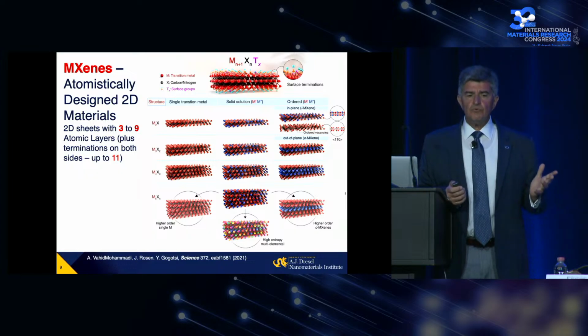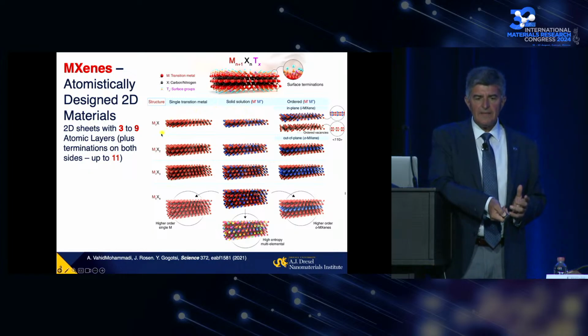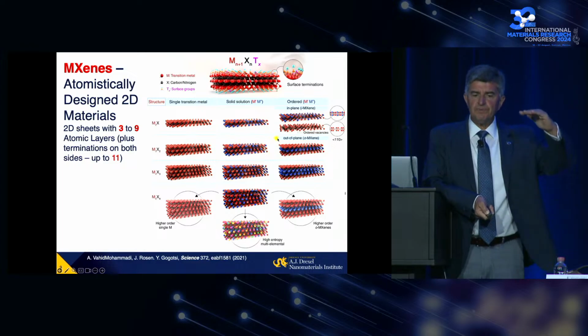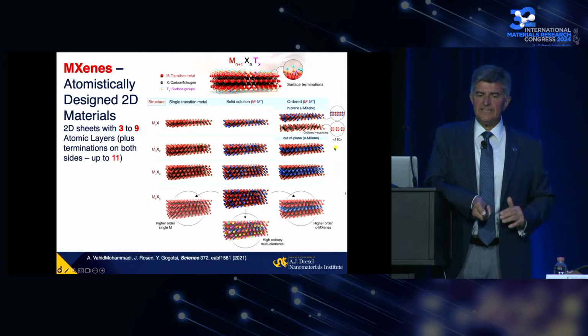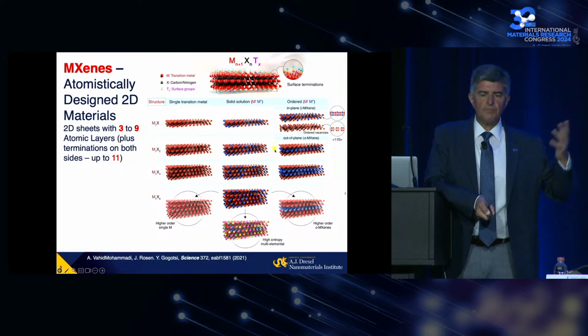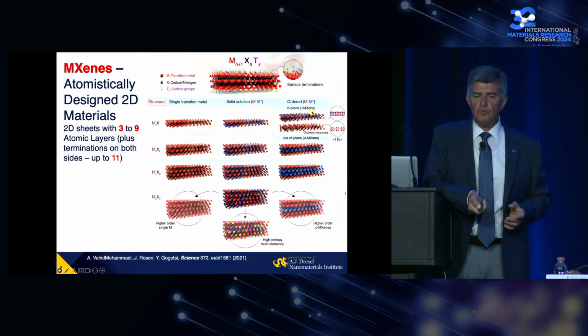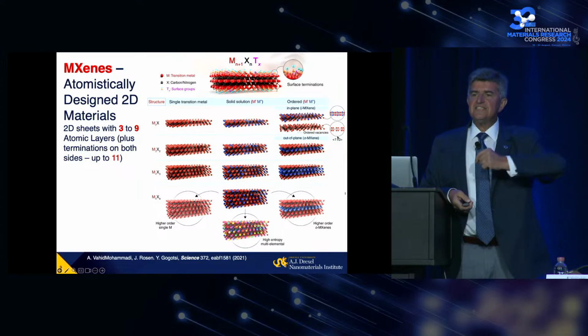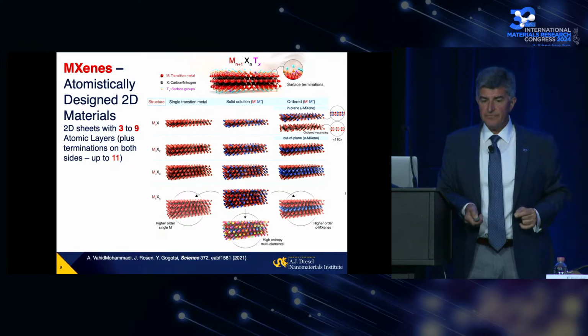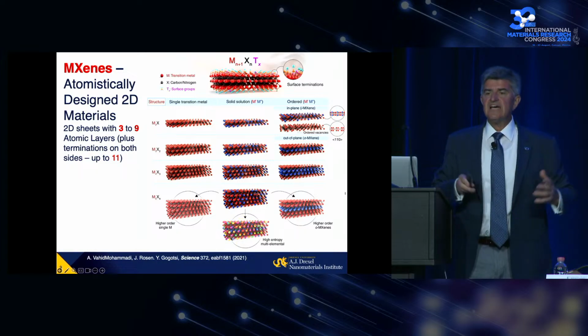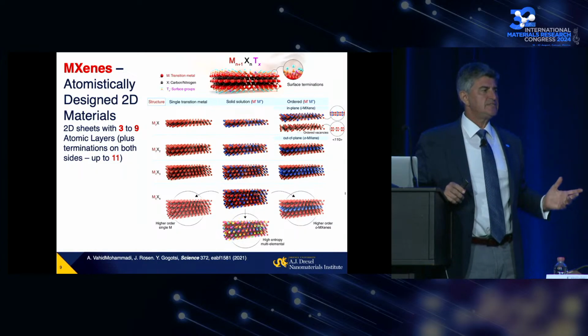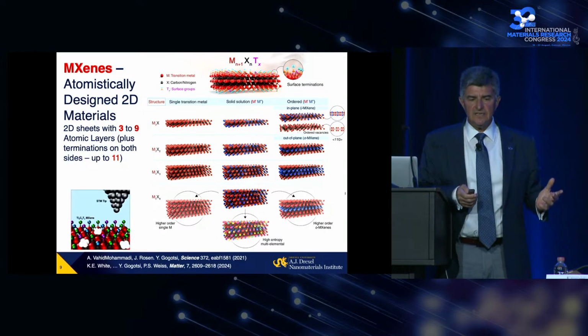Moreover, we're really moving to the era of atomistic design of materials, because we can make not only these simple basic structures, but atomic sandwiches out-of-plane ordered materials with, for example, one element like titanium on the surface, chromium or moly on the surface, and titanium in the middle. We can make materials with alternating atomic columns of different elements, or extract one of those and leave atomically thin trenches on the surface of the material. We can make high entropy MXenes with up to 7 different transition metals in the structure. And this is just the beginning.